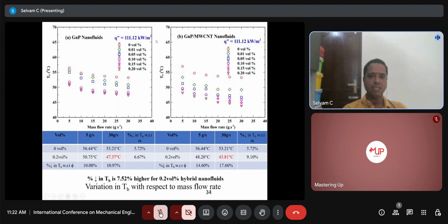With the increasing heat flux, the initial temperature is increasing, and from that it is reducing. From 56 to 47.37 degrees Celsius is reduced with the use of graphene nanofluids, and with the use of hybrid nanofluids we are getting 43.81 degrees Celsius from 56.44. So the reduction percentage is 17.66. We have to reduce more temperature; the reduction should be higher. So actually it is working with the hybrid nanofluid, significantly it is working.